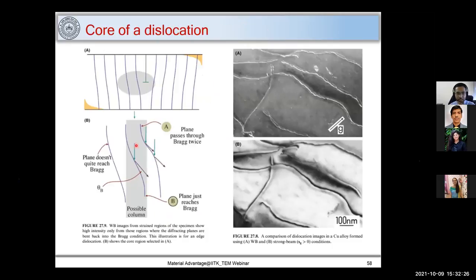So here in this case, you can see that when I image dislocations near to this region, the contrast will be much more, though the intensity is less. But if I widen here, I get maximum intensity, but I cannot resolve these dislocations. So this is a drawback if you use more area near the core of the dislocation.